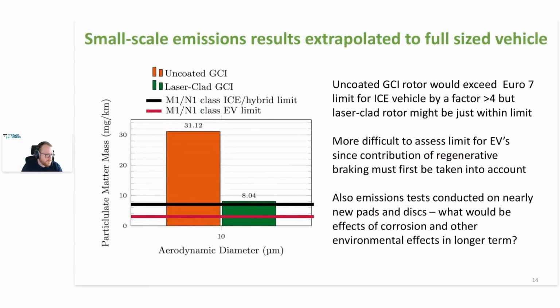All very encouraging results. So these emission results can be extrapolated into a full-size test vehicle by applying the appropriate scaling factor and assuming that the vehicle is fitted with 4 similar disc brakes. The results of this extrapolation for both standard gray cast iron and laser-clad rotors are compared with the current Euro 7 limits in the figure on the left. As you can see, the emissions for the uncoated rotor are predicted to be 4 times more than the limit for internal combustion engine vehicles.